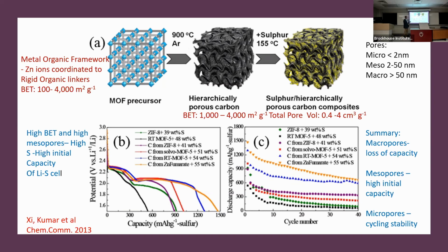We immediately saw that even though they're all MOF precursors, they all have different surface areas and a different distribution of those different pores. Looking at that, we worked out that whenever you have a high BET and high mesopores, it can take a high amount of initial sulfur. It's got a very high initial capacity, which is given by the first cycle of that cell.